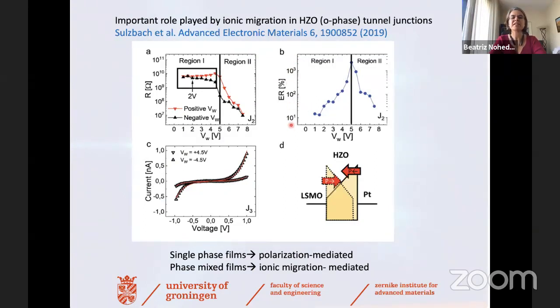Very, very large changes in electroresistance have been found by the group of Ignacy Fina and Josep Fontcuberta at ICMAB. They find a region of low voltages, particular voltages where this electroresistance effect is particularly large. They explain this as the coexistence of two effects: a part that is polarization-mediated, due to the ferroelectric nature of the material, but also the influence of ionic migration in the material.